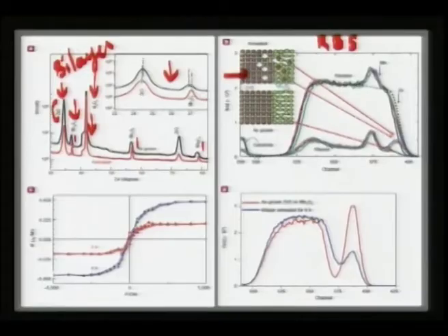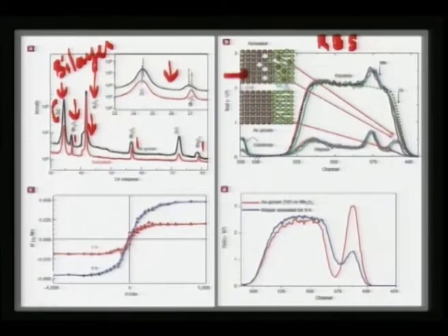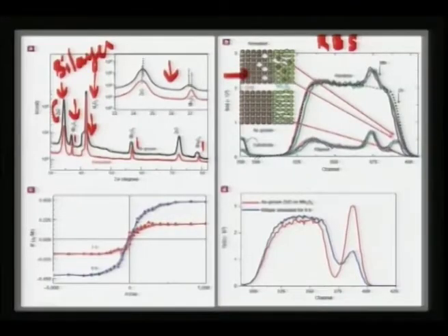So, this is the situation for a ZnO layer, which is capped with the Mn3O4 layer. This is as grown. You have alumina, then you put a thick ZnO, and then on the top you put Mn3O4. Now, the channeling profile will be something like this. The dotted one here is the simulated spectrum for 2% manganese oxide doped ZnO. The simulated spectrum has to be something like this, but what you see here for an as grown film